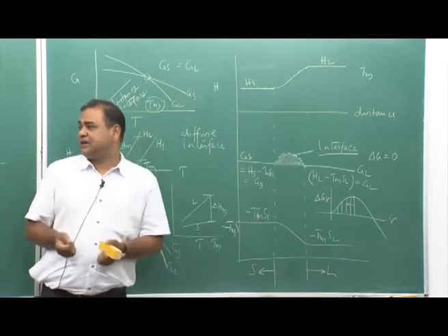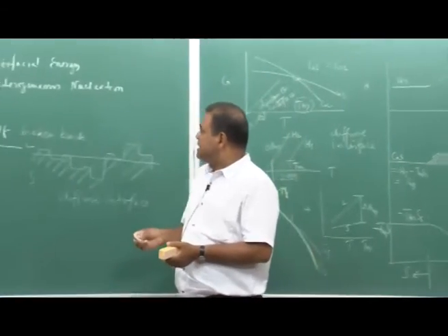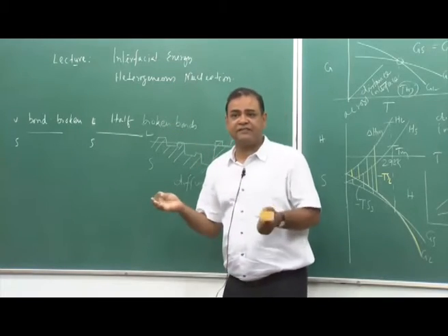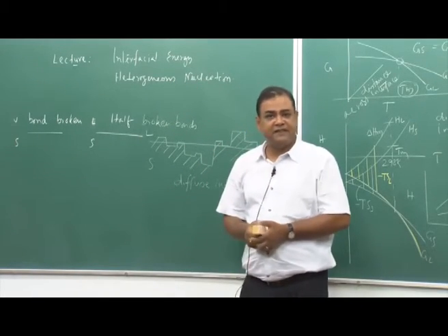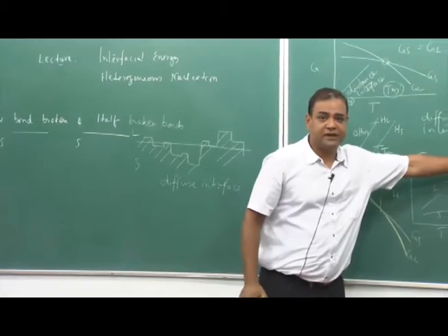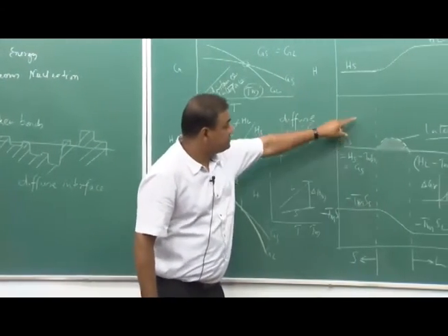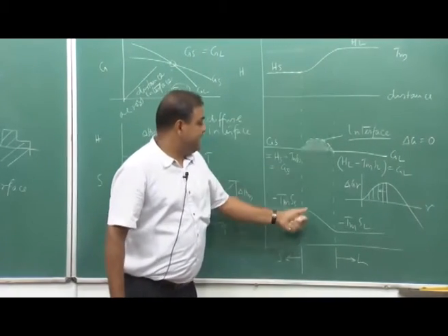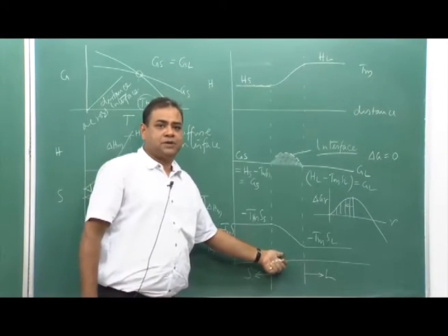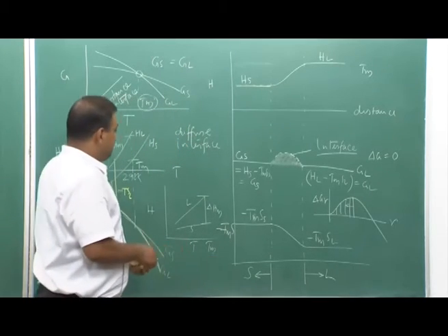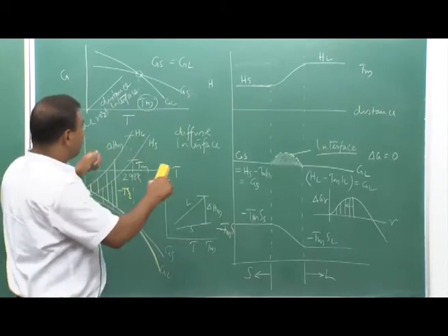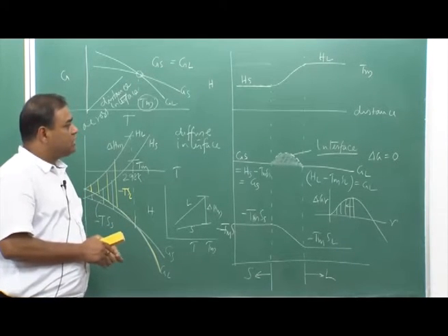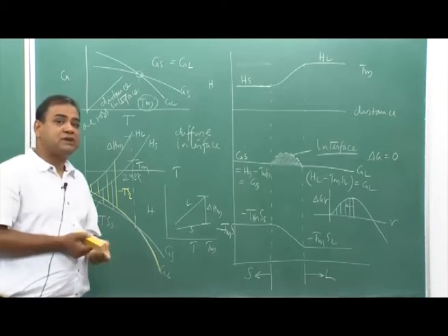We wanted to understand that particular situation, what that interface energy is. So, what is the physical essence of interfacial energy? This is from thermodynamic principle, and it is coming due to the difference between the H and TS terms. Now, from the overall discussion, we get to know why the interface is so critical.